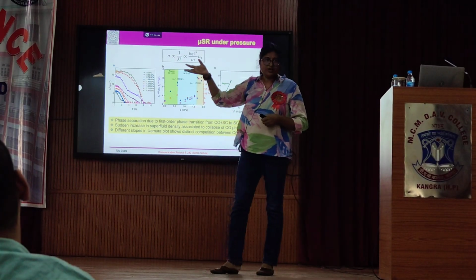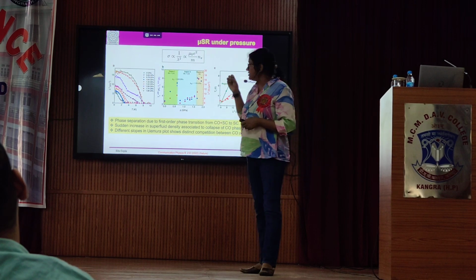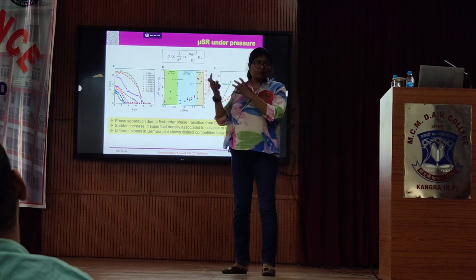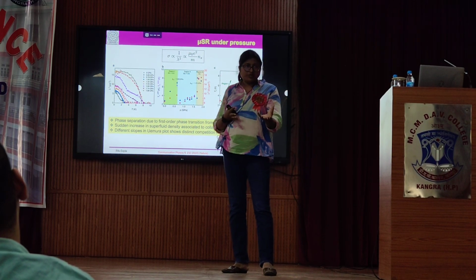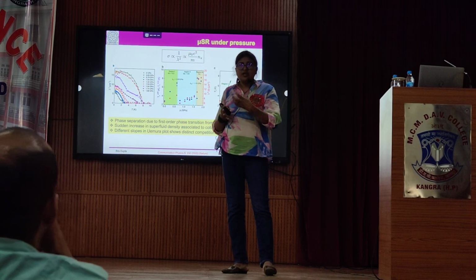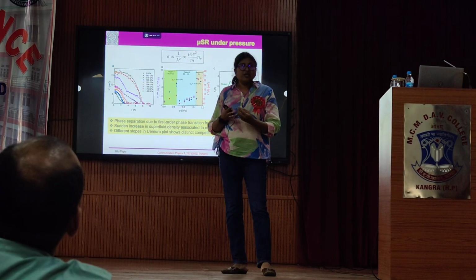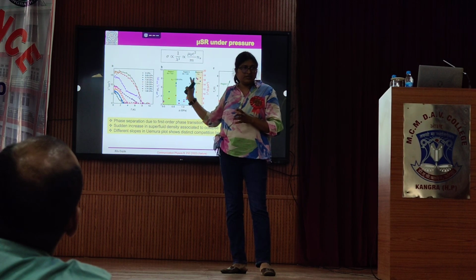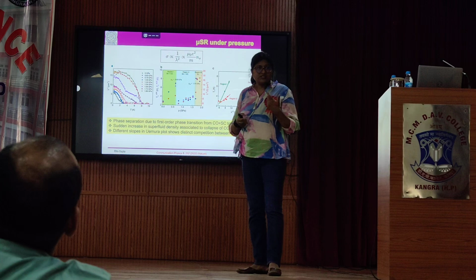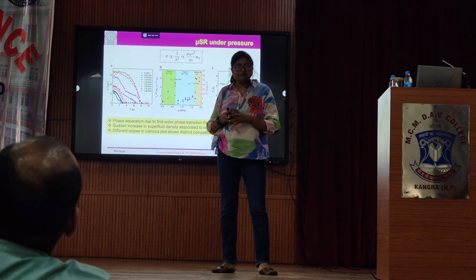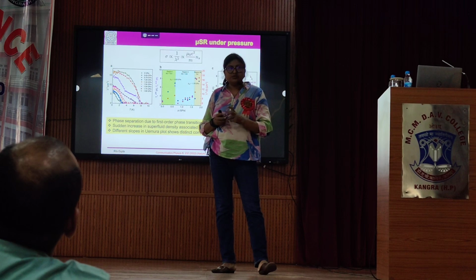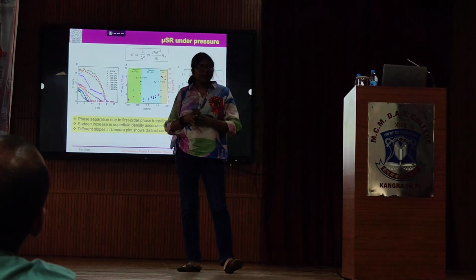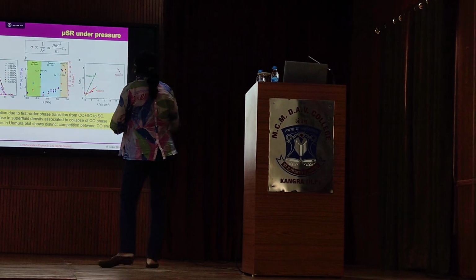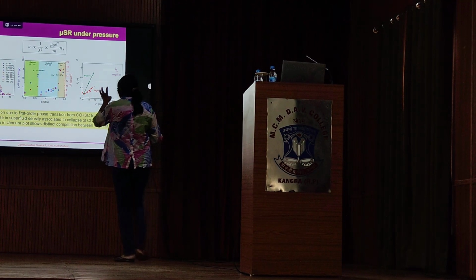The charge order which was present at high temperature got suppressed. Just because that charge order is no longer there, that means there are more electrons available for superconductivity, right? There will be more Cooper pairs, and that's why the TC is increased. Okay, so this is one way to increase TC. This is the way people are doing it in many materials, to suppress the competing phase from the material. Okay, and then there are some more results, but I will not go into details of those.